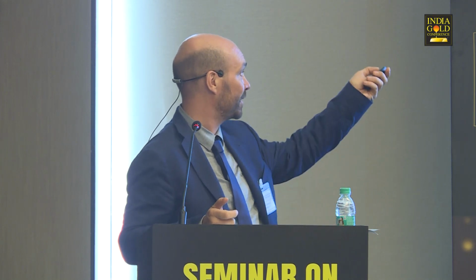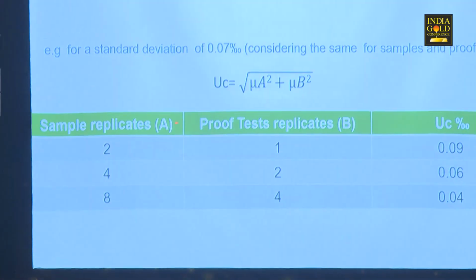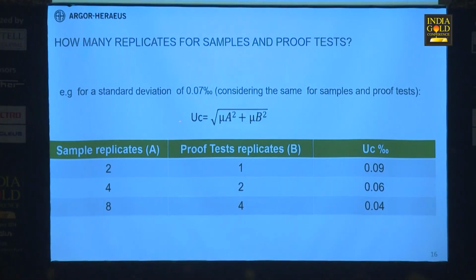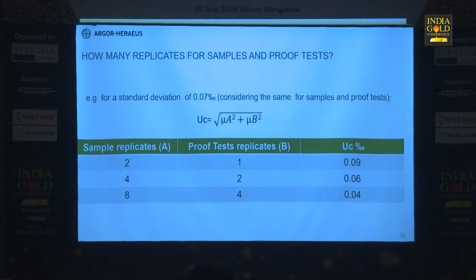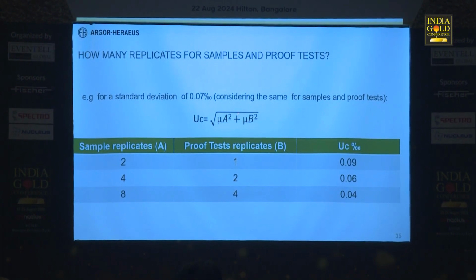If we start using a method that has a standard deviation of 0.07 per mille, it's just an example, and we consider the same standard deviation for the sample and for the proof test, we can use this formula to calculate the UC. Obviously, this must be divided by the square root of the number of repetitions. So at the end, we have these numbers. If we use, starting from 0.07, 2 replicates for the sample and 1 replicate for the proof test, at the end we will get 0.09 per mille.